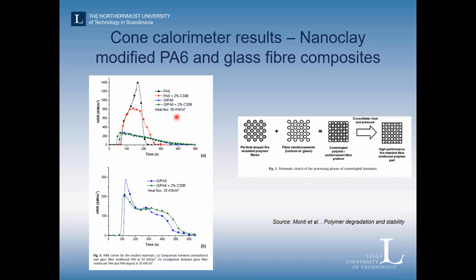And in this case, we have a heat flux of 50 kilowatts per square meter. In the lower one, there is 35 kilowatts per square meter. What can be noticed, this is then for PA6, the neat polymer, and this is with some nanoclay additive that is added to the polymer. But typically, we can notice the ignition time. The time to ignition here is below 100 seconds, around 60, so sort of 1 minute. And we notice the scale here is 500 seconds. The heat release rate goes up to around 1400 kilowatts per square meter.